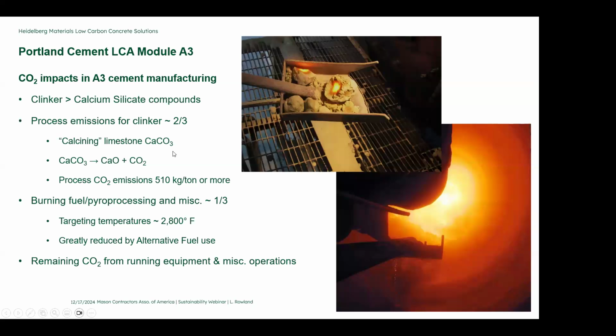So calcium wants to be coupled with CO2 in its natural state. Calcium will typically not be just all by itself. It will be calcium carbonate. It's oysters, whatever, marble, limestone, they're all different types of calcium carbonate, right? CaCO3 is that chemical compound that is essentially limestone. There are other materials in there as well, but that's the primary source of our calcium, and that's what we're looking for. The calcination is when we heat that material up very high, the CO2 is released.